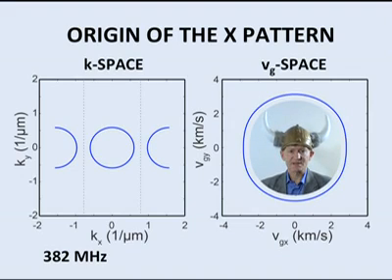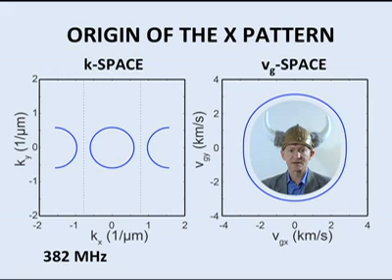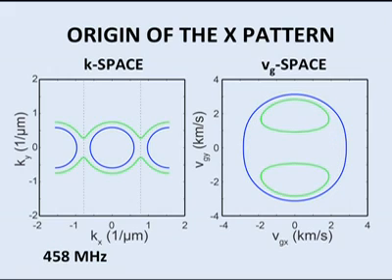In group velocity space, shown on the right, we plot the speed of a sound pulse. In this approximate analytical approach, at low frequencies we get rounded shapes in both spaces, meaning the ripples are roughly circular. As the frequency increases, we hit a band gap in the horizontal direction — a direction waves can't travel — visible through the opening of the circles in k-space. And this makes two circles in group velocity space.